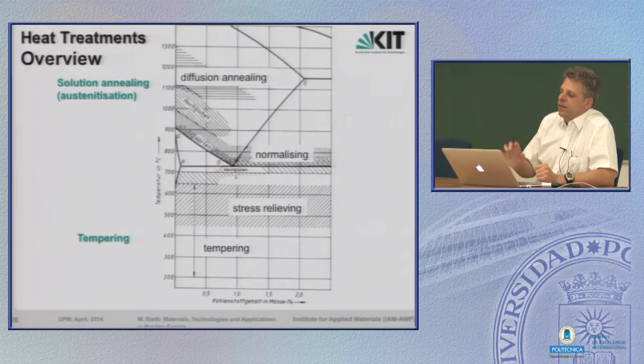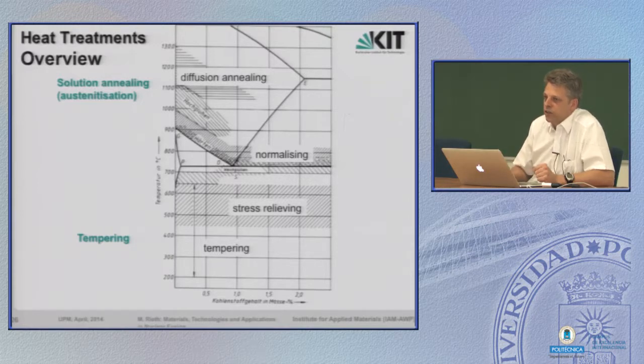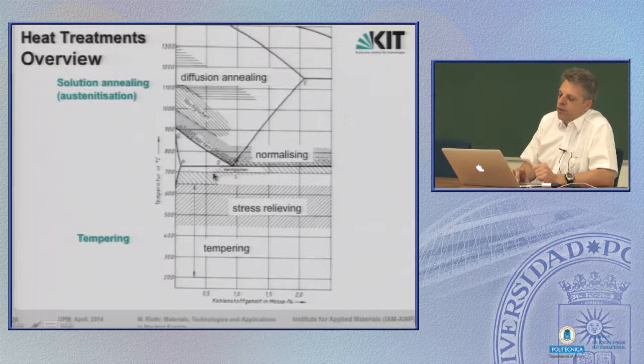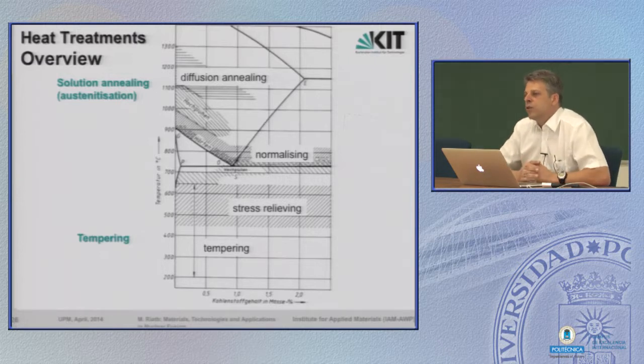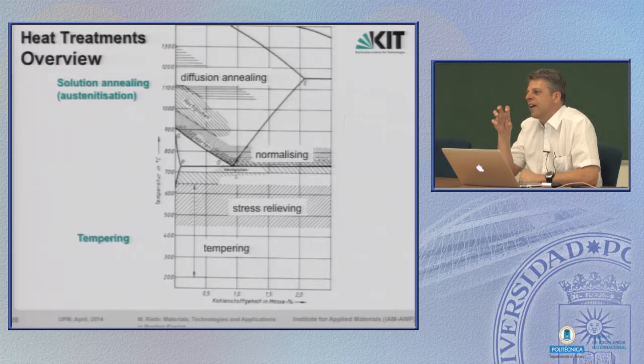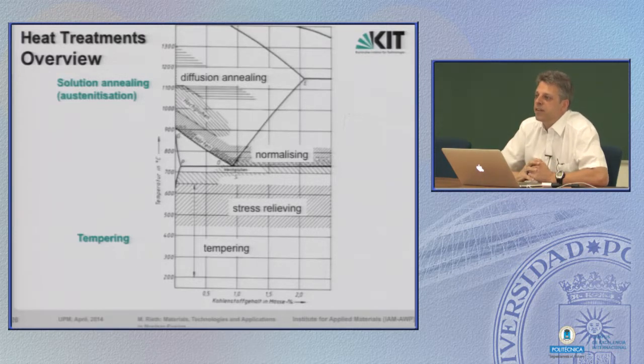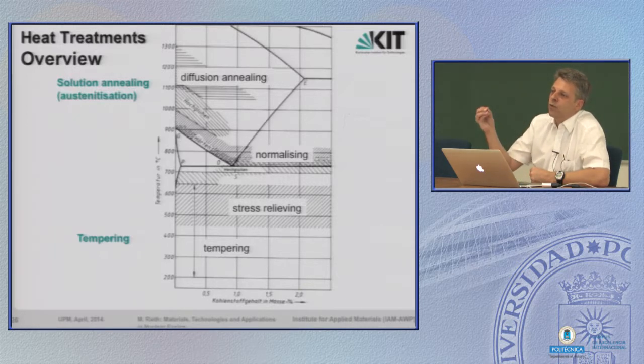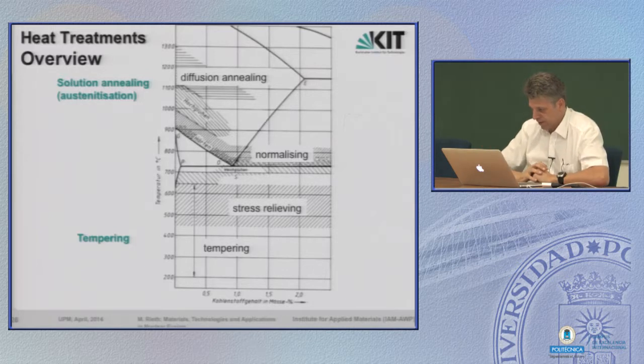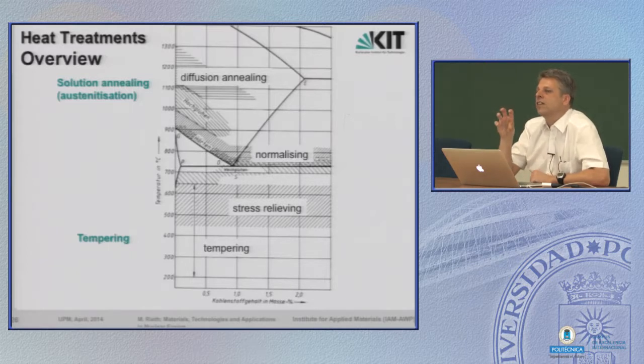Then the martensite can also be changed by tempering. Of course, you have to do the tempering below the transition line from alpha to gamma, but if you do it in this temperature range, and do it for a long enough time, then remember the carbon is captured in this tetragonally bended BCC lattice. If you give time or have time enough to wait, do tempering, let's say at 400 C or so, in these iron-carbon steels, then the carbon goes out of this lattice. It diffuses somewhere, we will see later where it goes, but it goes out of the lattice, and what is left over is a more or less carbon-free lattice again.